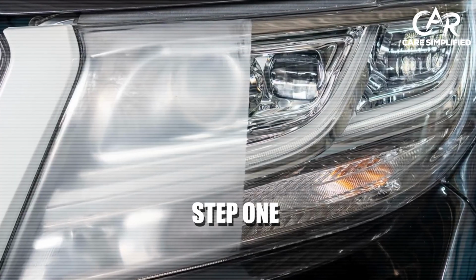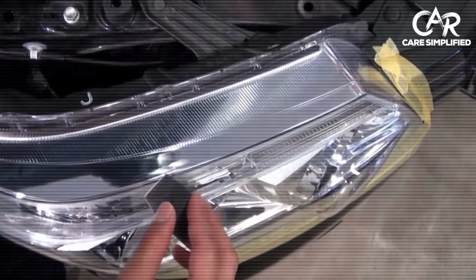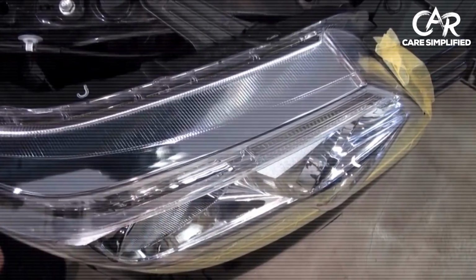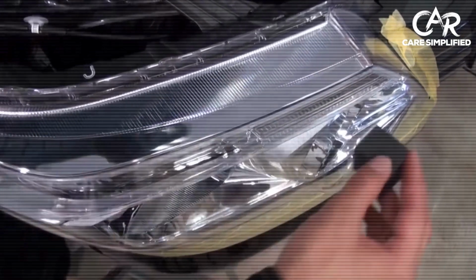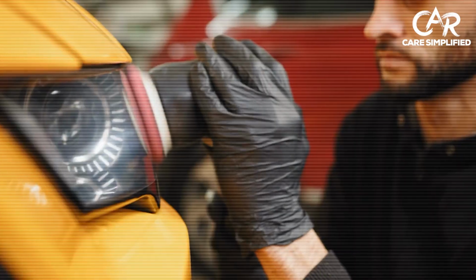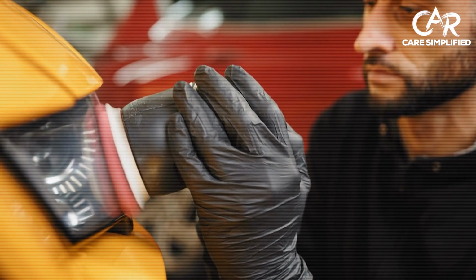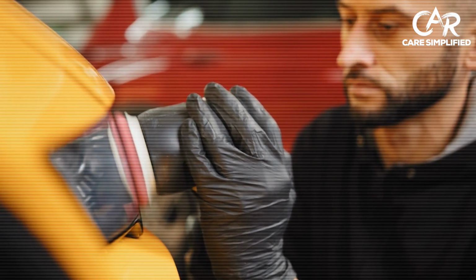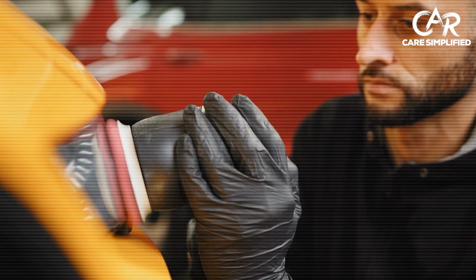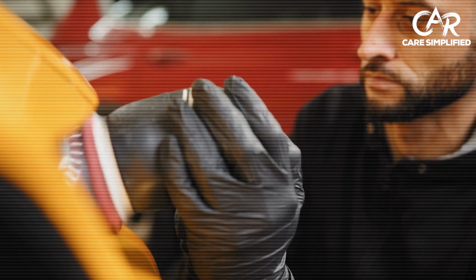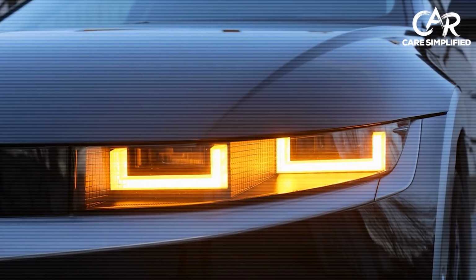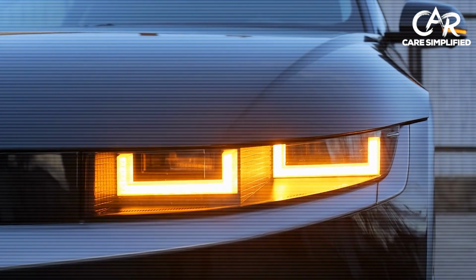Step 1 is surface preparation. You need to remove the damaged oxidized layer of polycarbonate to expose fresh, clear plastic underneath. The professional approach is wet sanding with a progressive grit sequence. You start at 800 grit to cut through heavy oxidation, move to 1500 grit to refine the surface, then 2000 grit, and finish at 3000 grit. Each level removes roughly half the scratch depth left by the previous one. You keep the surface wet throughout to prevent heat buildup and wash away debris. The result is a uniformly smooth lens ready for coating.